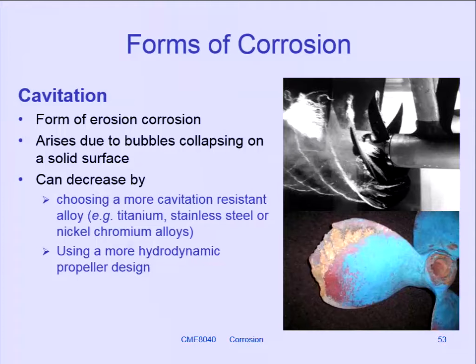There's more damage out at the edge of the propeller than there is near the centre of the shaft, because the radial velocity is so much higher on the outer edge. What you quite often find, and it's not very clear on this one, is that whichever is the leading edge of the blade tends to get more damage than the back end of the blade.